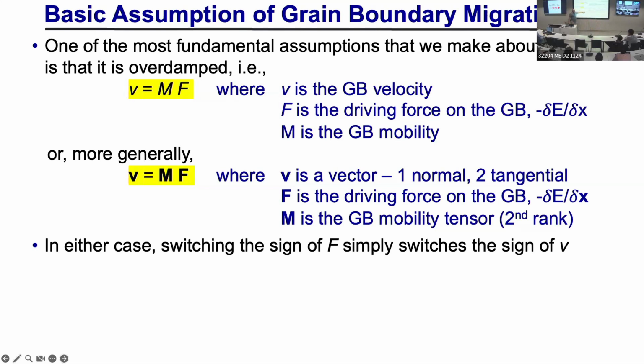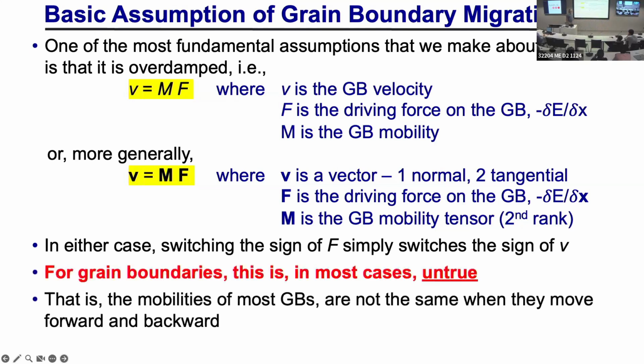Now, one of the necessary conclusions of all this is if I switch the sign of the driving force, the boundary moves with the same velocity in the opposite direction. Well, it turns out that this is rarely true. Even though we always assume it, we use it in all sorts of macroscopic simulations. And in fact, it's rarely true for most types of defects, whether we're talking about dislocations or two-phase interfaces or grain boundaries. So the mobilities are basically not the same when you move the grain boundary this way and that way.